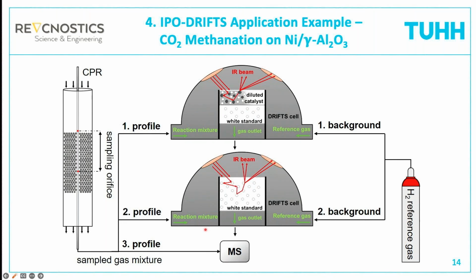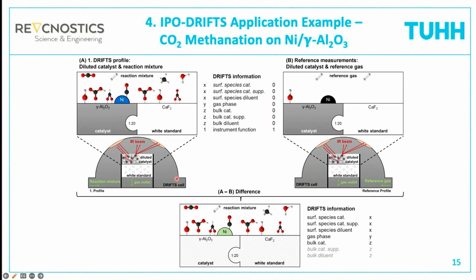And then we repeat the set of experiments, but this time we replace the catalyst filling by the pure diluent, by pure calcium fluoride. First, we again connect to the CPR to perform the isopotential measurement, and then we repeat for the temperatures given the measurement in the hydrogen reference gas. And we always check with the mass spectrometer what is the conversion. So once we measure directly behind the CPR, and then we also measure the conversion when the CPR mixture goes additionally through the drift cell. And what is the purpose now of these 4 measurements? This I try to illustrate here.